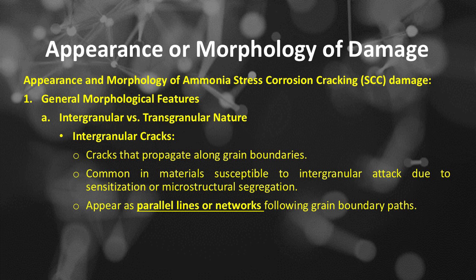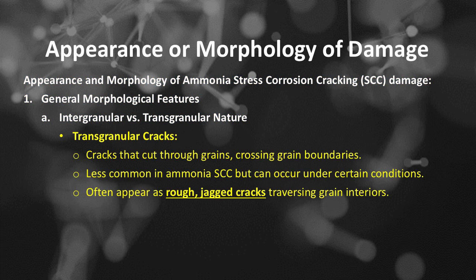For intergranular cracks, cracks that propagate along grain boundaries, common in materials susceptible to intergranular attack due to sensitization or microstructural segregation. They appear as parallel lines or networks following grain boundary paths. For transgranular cracks, cracks that cut through grains, crossing grain boundaries, less common in ammonia SCC but can occur under certain conditions, often appearing as rough, jagged cracks traversing grain interiors.